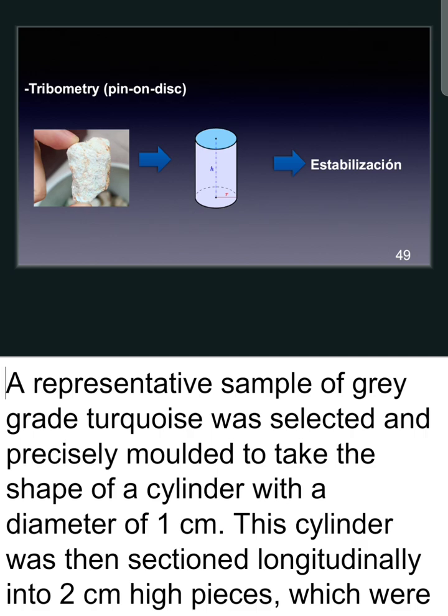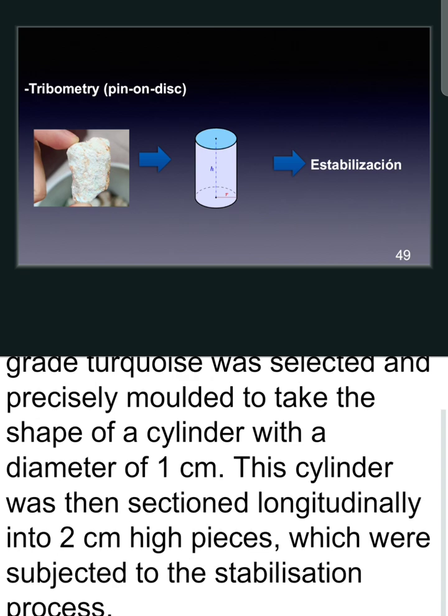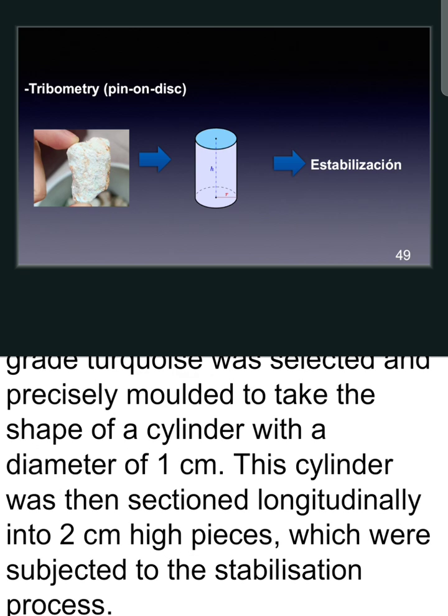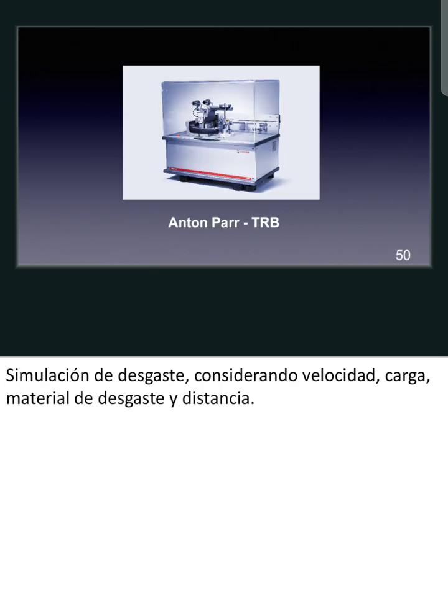Talking about the tribometry pin on disk, a representative sample of gray grade turquoise was selected and precisely molded to take the shape of a cylinder with a diameter of 1 centimeter. This cylinder was then sectioned longitudinally into 2 centimeter high pieces, which were subjected to the stabilization process. The tribometry was done on the Anton Paar TRB.